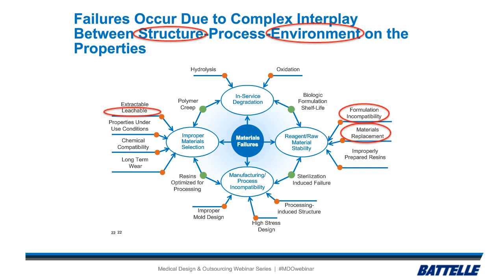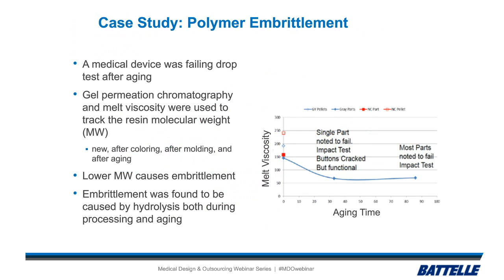So I have one more example to go through here, and this is a polymer embrittlement example where there was a medical device that was failing a drop test after aging. So one of the materials on this was failing the drop test. It wasn't failing before aging, but just after. It was a PBT material, which is a polyester, which is susceptible to hydrolysis, which gives you shorter molecular weight and causes embrittlement. We were able to find out the molecular weight of the material both before and after aging by gel permeation chromatography. Then we also used melt viscosity, much easier to measure than gel permeation chromatography. So we showed that those correlated, and then we used melt viscosity to show how much molecular weight we lost